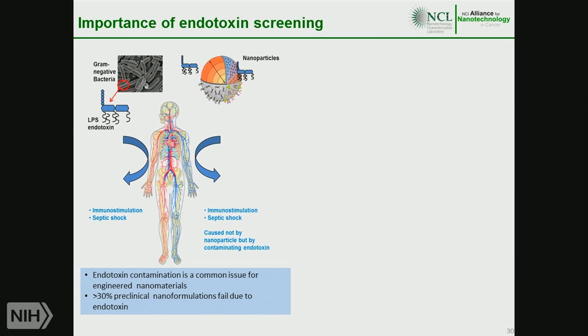Another challenge related to particle characterization in preclinical stage is contamination with endotoxin. Endotoxin is a component of gram-negative bacterial cell wall. It is a very common contaminant in nanomaterials. In fact, around 30% of preclinical formulations are contaminated with endotoxin. Endotoxin can be present in nanoparticle suspensions or solutions, or it can bind to the particle surface. Especially cationic materials are prone to endotoxin contamination because endotoxin is anionic. So just due to the electrostatic interaction, anionic endotoxin binds to the surface of the cationic particles.